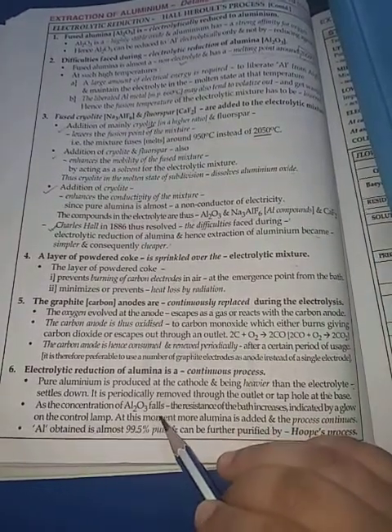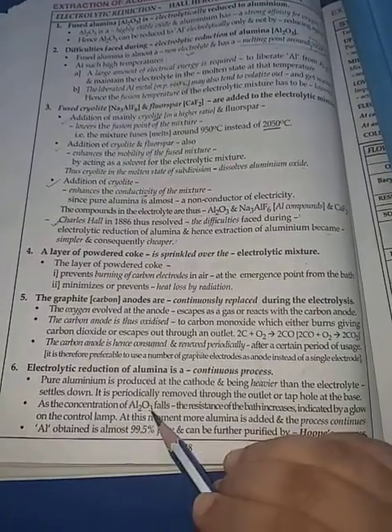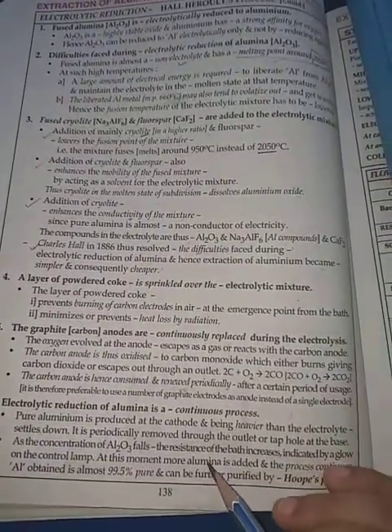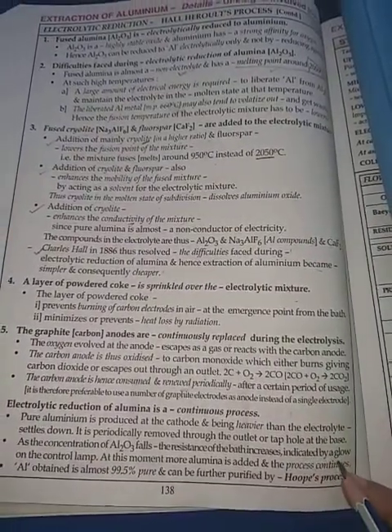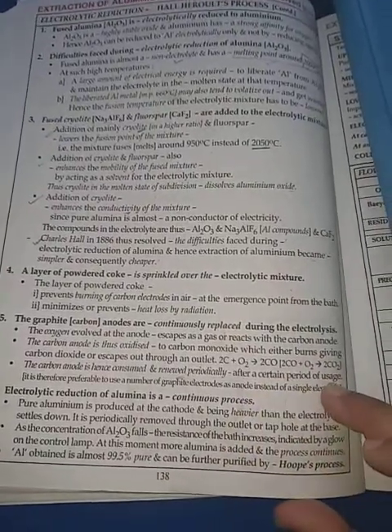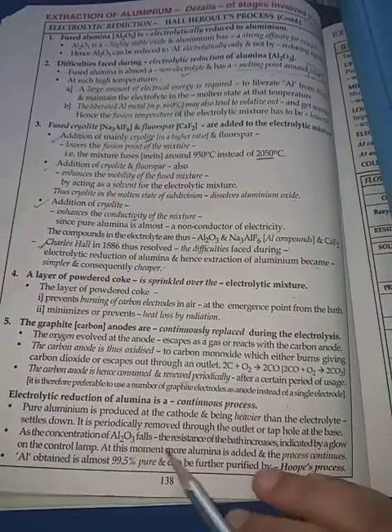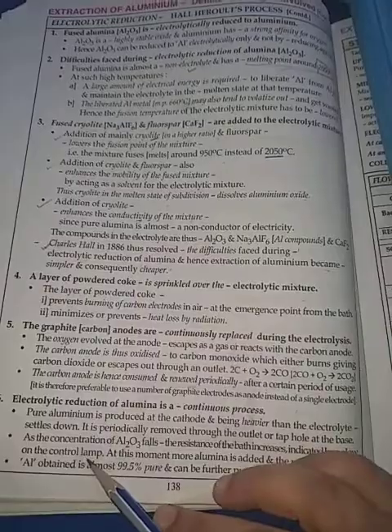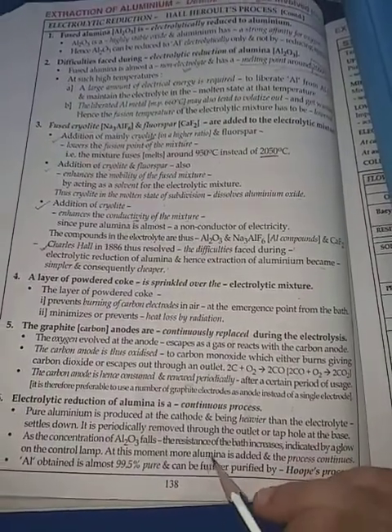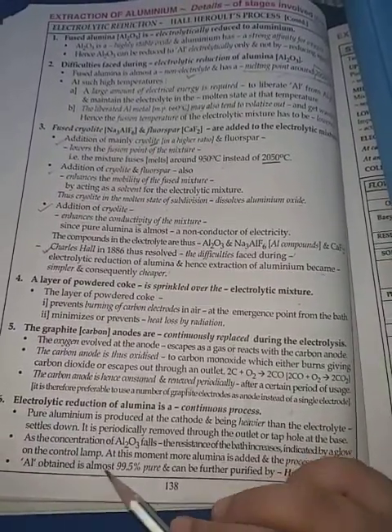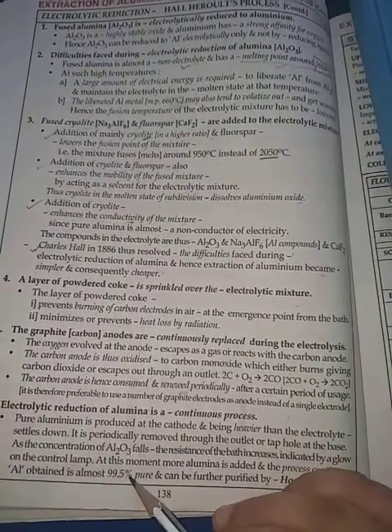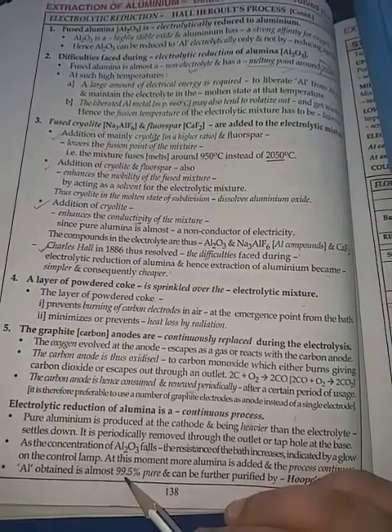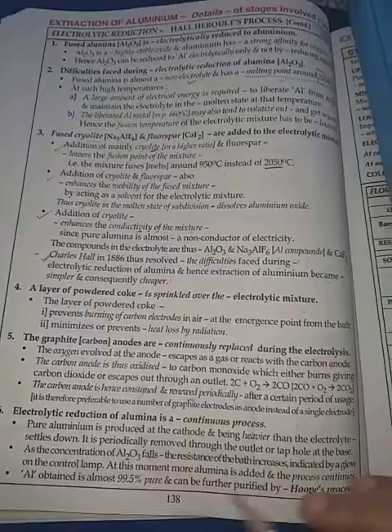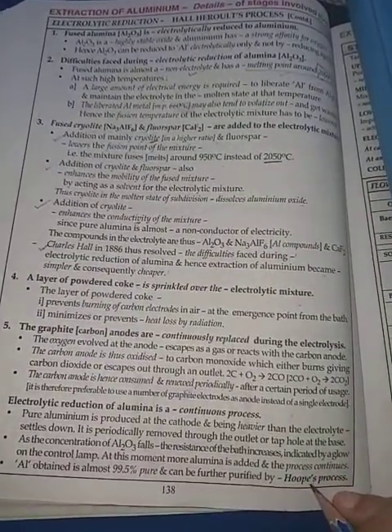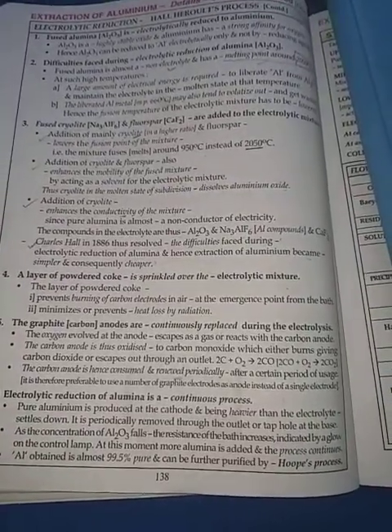As the concentration of Al2O3 falls, if it is consumed and very less amount of this Al2O3 is there, the resistance of the bath increases and is indicated by a glow on the control lamp. A control lamp is there. In our previous video also I told you about this, and at this moment it is indicated by the glow of the control lamp, and at that time pure alumina is added and the process continues. Aluminium obtained here by this Hall-Heroult process is 99.5% pure, but if we want to obtain aluminium of 99.9% purity, then after this Hall-Heroult process we do the Hoope's process, and after this Hoope's process the aluminium obtained is 99.9% pure.